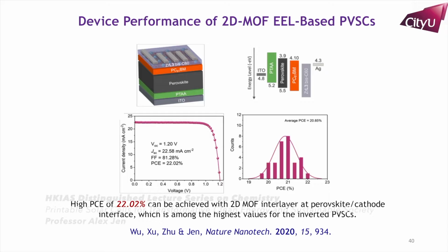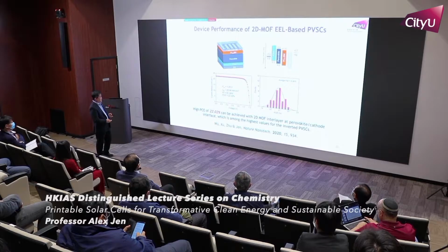So this means you can use that as a protection layer, and then we also utilize this as a charge extraction layer. This can have very good contact with the top silver electrode. As a result, you can get a very high efficiency out of this.